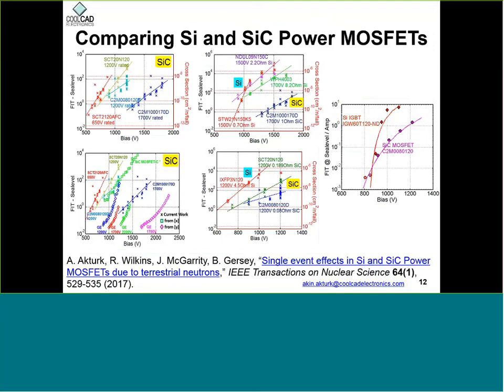And here I compare some silicon carbide power devices with some silicon power devices. This is a busy picture, but the main takeaway point is at high biases for the similar silicon and silicon carbide parts, silicon has much higher failure time values. So that means at high biases for the same kind of device, silicon part is much more likely to fail within a given time.